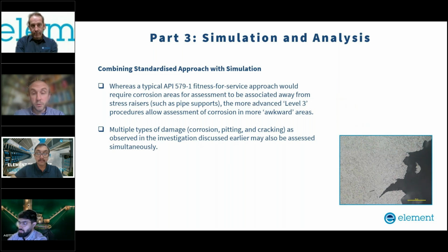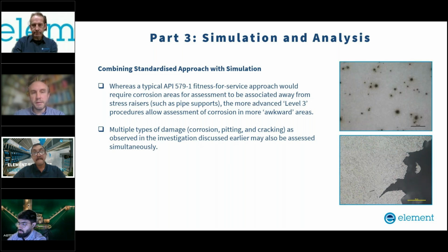And we can also take advantage of the fact that we can actually assess and model simultaneously areas of corrosion, pitting, and crack-like features, so that we can identify what the sort of simultaneous effect that they're having on one another is in terms of their crack driving forces, and compare those to the relevant material resistances, whether that be a sort of function of the tensile properties, or whether it be a fracture toughness type property.